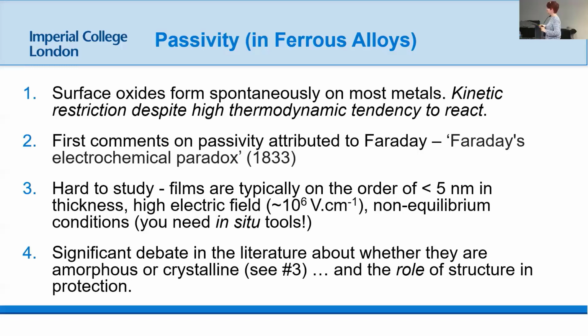This debate was further exacerbated when you started to look at stainless steel, and really from the work of Jerry Kruger, who did a lot of work on stainless steels and really developed this idea that amorphous films were somehow better, and that chromium made the films amorphous, and that amorphous structure gave you resistance. Okay, so a word of caution for PhD students here. If you go back and read Jerry Kruger's first ever paper, where he analyzed passive films, he had absolutely the right answer. And then with time, as the idea of this mechanism kind of overtook the community, he forgot his own data. He was a really strong advocate that passive films on chromium alloys are amorphous, even though his early data showed that not to be true. So it's an interesting exercise to work backwards through his papers.